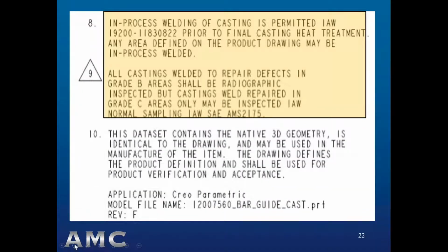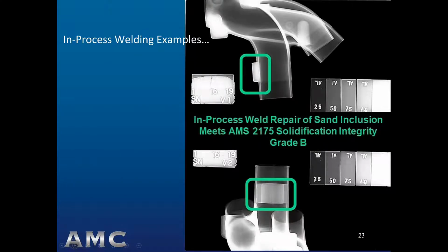Here's a well-crafted drawing note specifically allowing in-process weld rework and differentiating grade B and grade C solidification areas in accordance with AMS 2175. Returning to the same example of the in-process weld rework of the aluminum casting with the sand inclusion defect, here is the non-destructive testing documentation that the weld repair we see meets AMS 2175 grade B solidification integrity. Now please meet our casted teammate, Keith Sturgill.